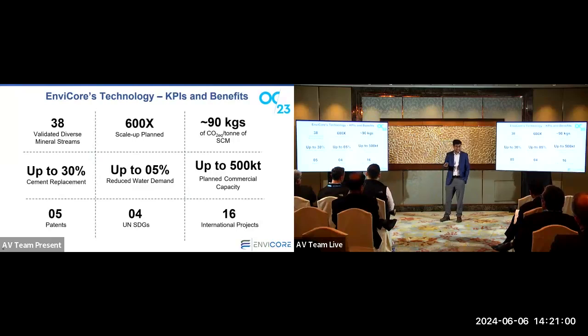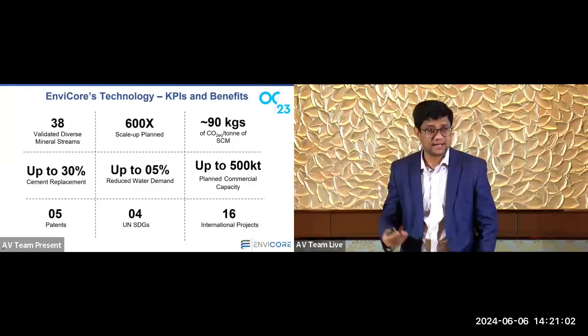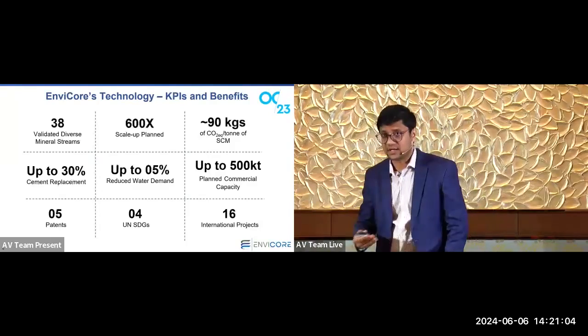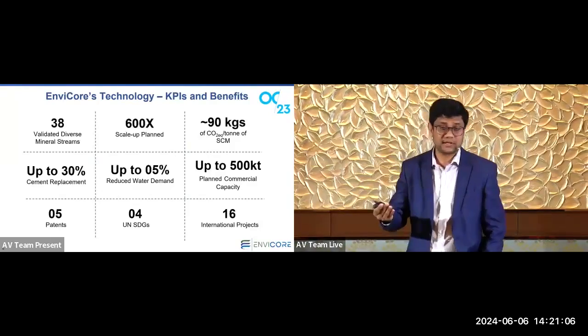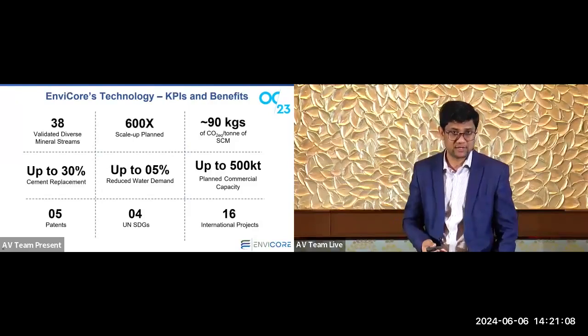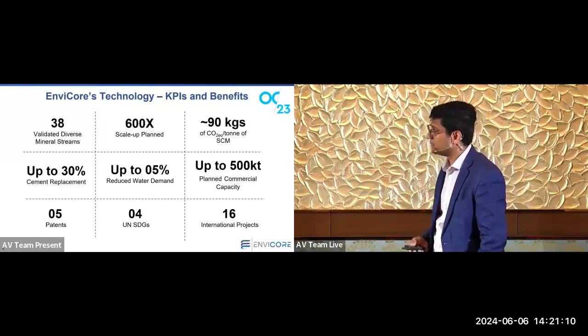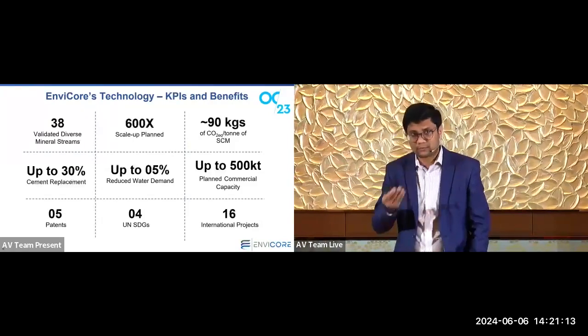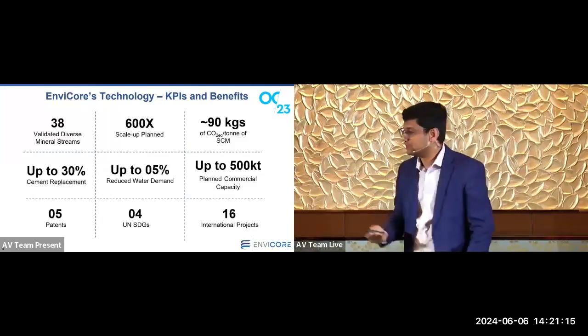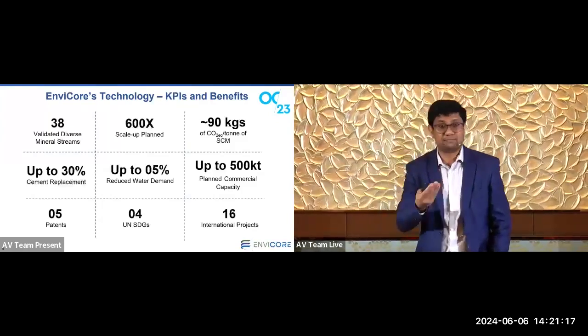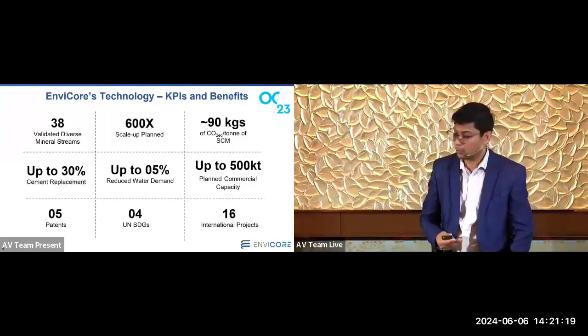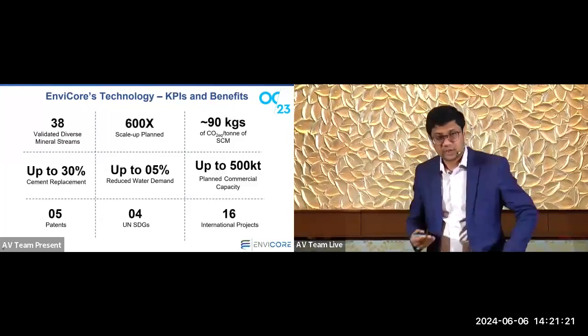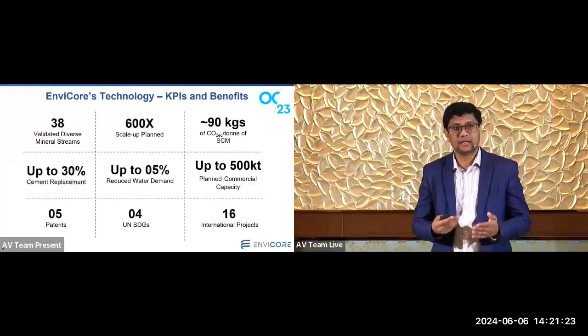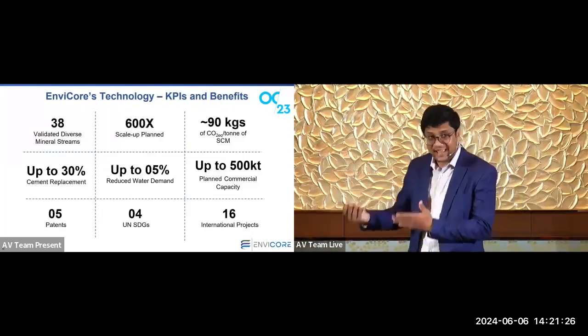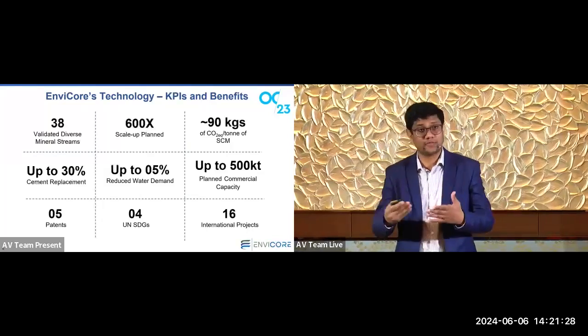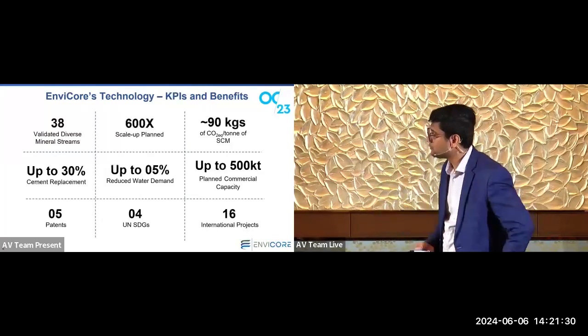Our idea, again, is to maximize the replacement level. We have done independent third-party testing on certain material that can go up to 30% cement replacement in a mortar and concrete mix. The additional benefit, along with increased performance, is the reduced water demand, which is quite beneficial for both concrete and cement producers. So we are trying to come up with a holistic solution to provide this decarbonization effort while staying good on the durability and performance side as well.